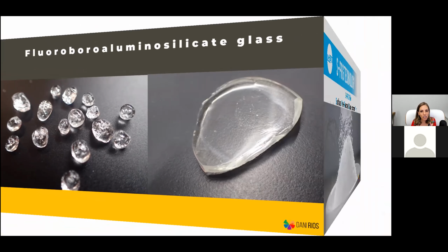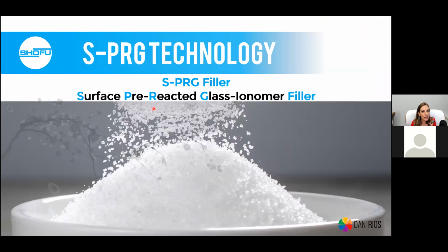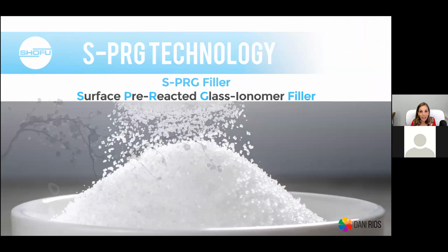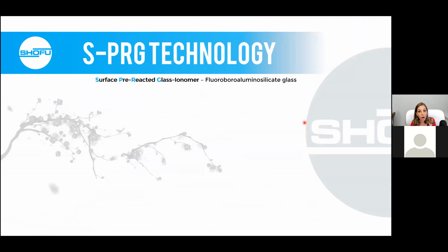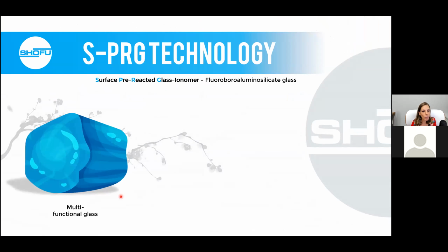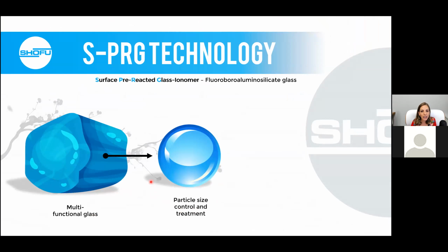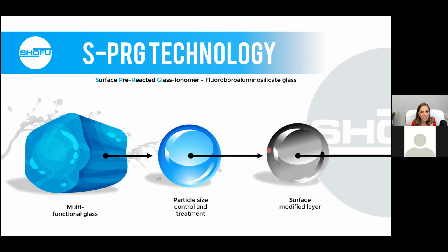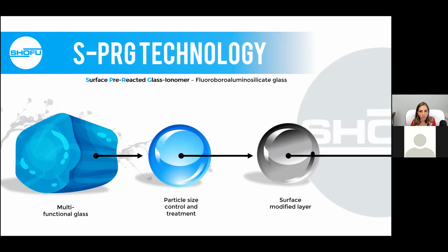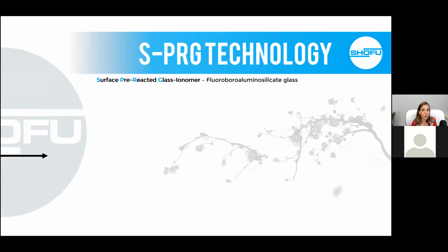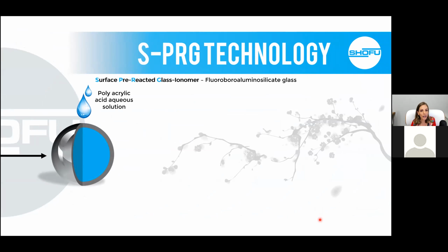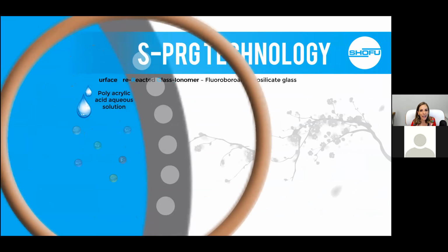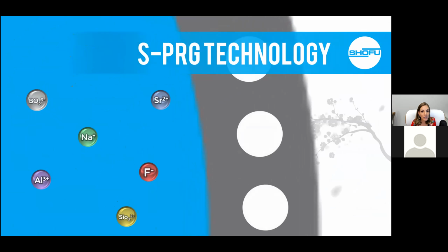Let's understand what is S-PRG filler. It means surface pre-reacted glass ionomer filler. Therefore, the surface pre-reacted glass ionomer corresponds to the final process in which this multifunctional glass is treated to achieve an adequate size. Then another layer is applied over the glass to protect it, named the modified layer. This modified layer is porous, and when sprayed with polyacrylic acid solution, the hydrogen ions will attack the multifunctional glass, releasing ions and starting an acid-base reaction that results in a matrix.